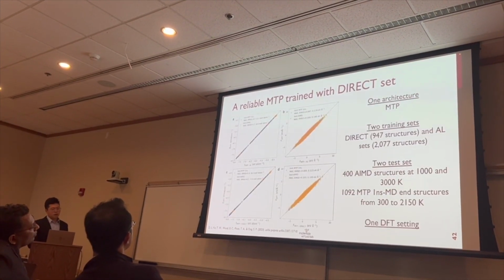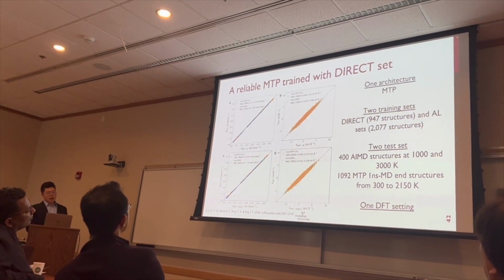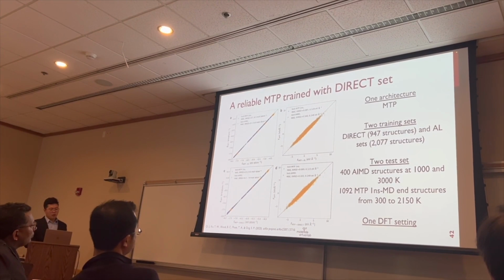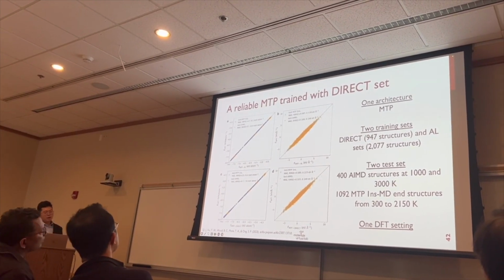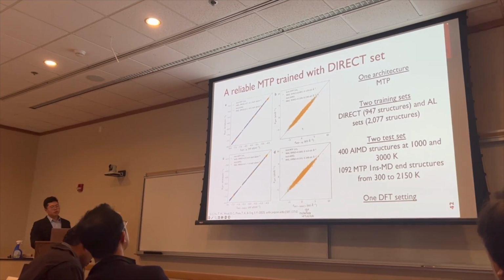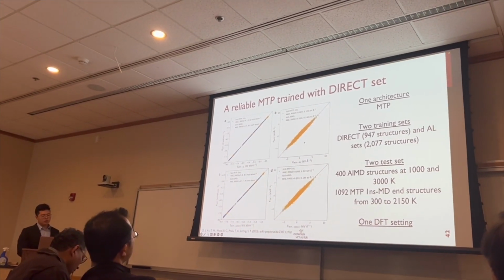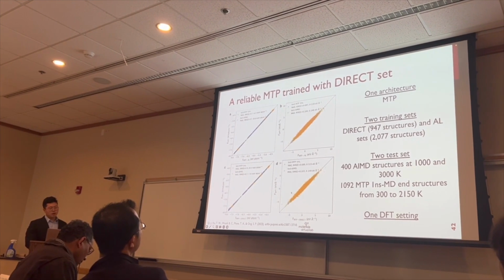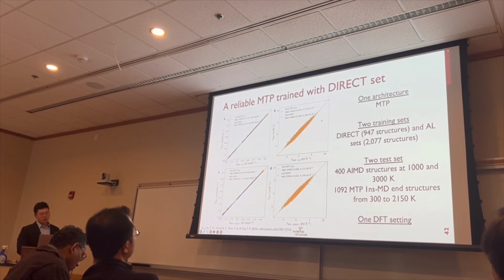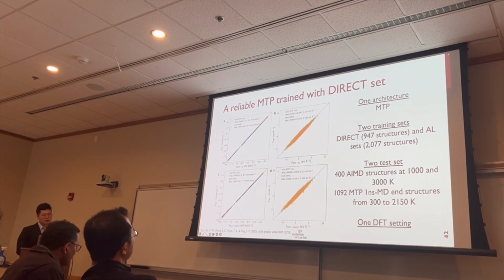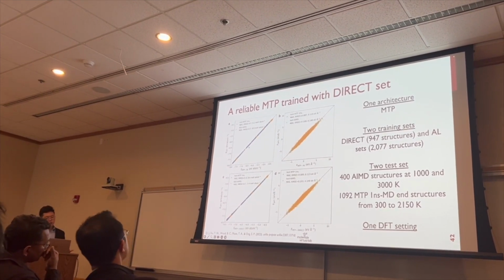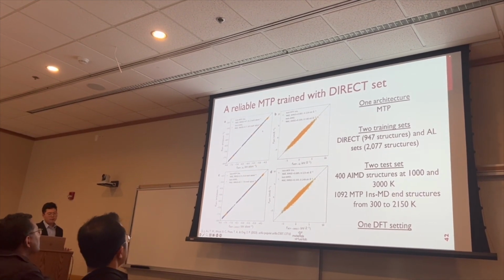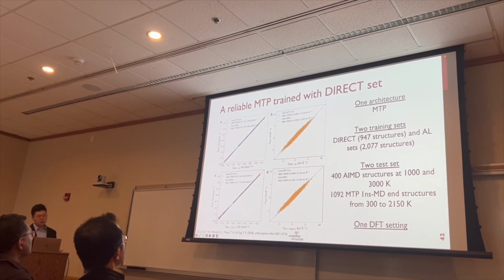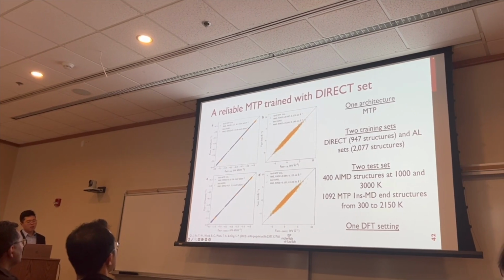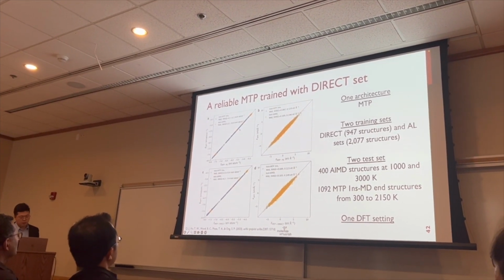We fit the MTP with two data sets. One training set is the direct training set, and the other is the active learning training set. By looking at this parity plot, we find that those two models both give very good matching with the DFT results. Especially for forces, those two models give almost the same results in terms of the MAE on the test set. For the energy, the MTP direct has 1 meV per atom larger error compared with the one sampled with active learning, but it's still quite reasonable.